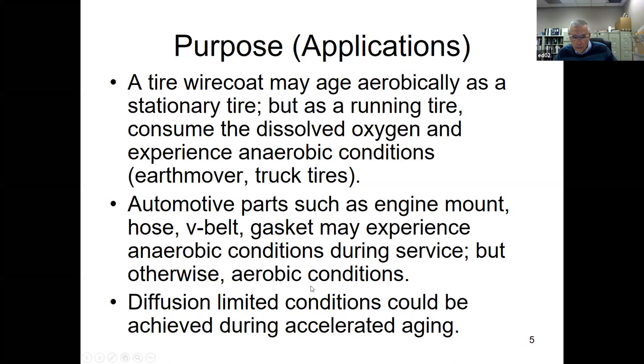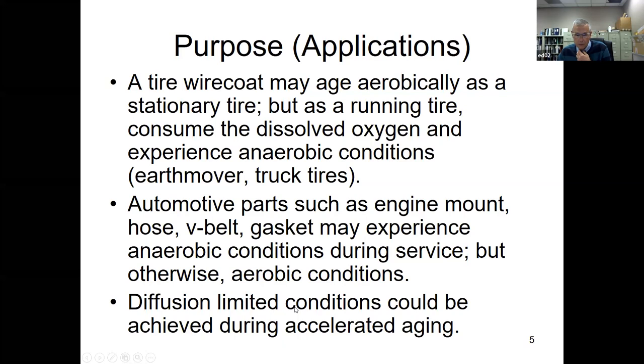This is background on applications where this might be important. A tire wire coat may age aerobically as a stationary tire, but as a running tire it consumes the dissolved oxygen and goes into anaerobic conditions — for example, in earth mover or truck tires. Automotive parts such as engine mounts, hoses, V-belts, and gaskets may experience anaerobic conditions during service and aerobic conditions otherwise. Diffusion-limited oxidation — where oxygen is consumed faster than it diffuses in — can also be achieved during accelerated aging.